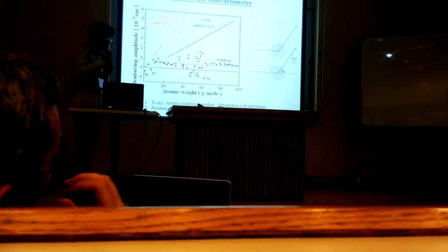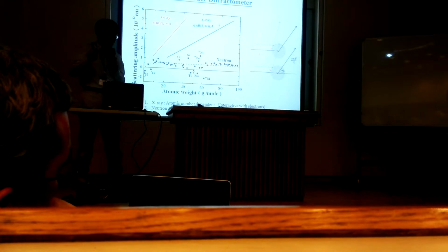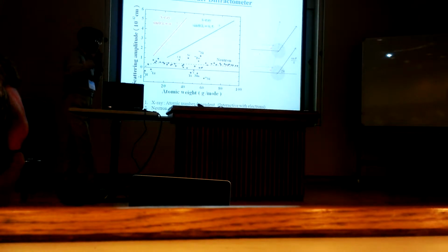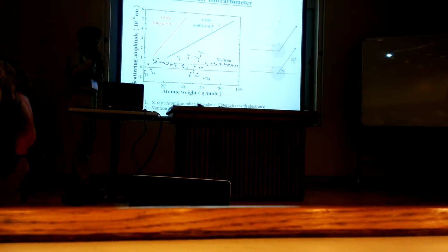When you go to high angle, the efficiency or intensity of X-ray would be very small. But for the neutron, as Professor Lee said in the morning, the neutron interacts with the nucleus, so it also has high efficiency at high angle. So when you go to high angle, that means the spacing is very, very small, and you can see very detailed information about the spacing between atoms. So that's the one thing I want to mention more.